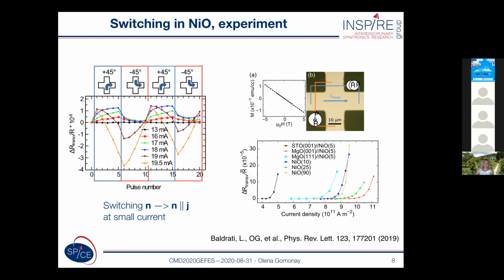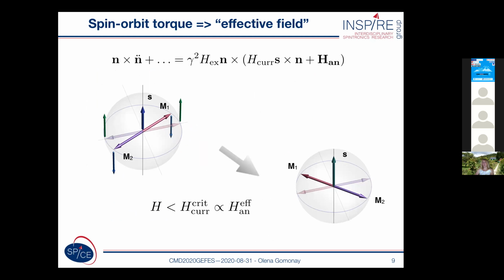If you look at the left panel, you see the resistance in a platinum electrode, which is associated with the 90-degree rotation of the Néel vector due to the current pulses. So the switching is there, and how can we explain this switching if the current creates only these dissipative torques? To answer this question, we started to analyze dynamics of the Néel vector for different geometries of the spin current, assuming that spin polarization can be directed in different ways with respect to the magnetization.